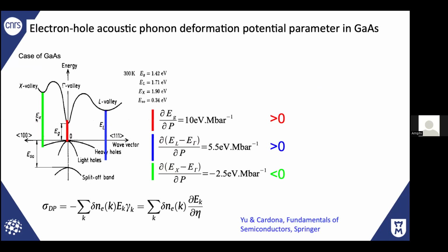And for semiconductors, for gallium arsenide, if you shine light and put electrons at, let's say, the zone center, or if you put electrons in the X or L valley, the deformation potential is different. For example, if you put electron-hole pairs just above the band gap, this has been measured by different techniques. The deformation potential in that case is positive, so you induce expansion of the semiconductor. But if you shine light, for example, to populate the X valley, the solid must contract. Of course, there is intervalley scattering, which is very fast, so according to me this has not been observed yet. But it is expected that if you populate that valley, you induce a contraction of the solid.